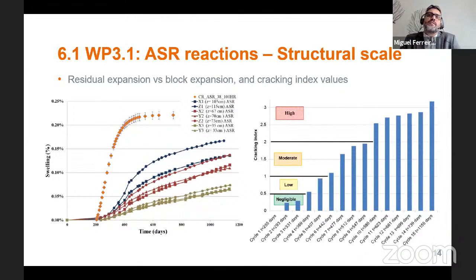We also observed that the extent of swelling is different. The residual swelling is 0.22% in the core, and in the block, in the upper block, if we consider the upper sensors to be the ones that are least affected by this restraint, so most probably those that are most likely to be comparable to the cores, it is 0.17%, and it's been estimated that it might stabilize at 0.185%. So another difference there. We also noticed that the swelling in the core stabilizes after approximately 400 days, whereas the block hadn't stabilized, and even after 900 days of conservation, it was still expanding. So clearly there is a scale effect on the reaction kinetics and on the swelling amplitude.